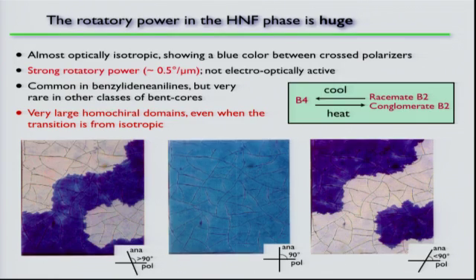So in a 10 micron cell, you get a 5-degree rotation, and you can see you've got these conglomerates. It's a conglomerate, so you have right-handed and left-handed domains. And if you uncross the analyzer and the polarizer, then you can see the rotated plane polarized light coming out. And remember that in chemistry, if we have a chiral material and we want to measure its rotation, we use a 10-centimeter path length. This stuff is doing this: you're getting 5 degrees in a 10-micron cell.